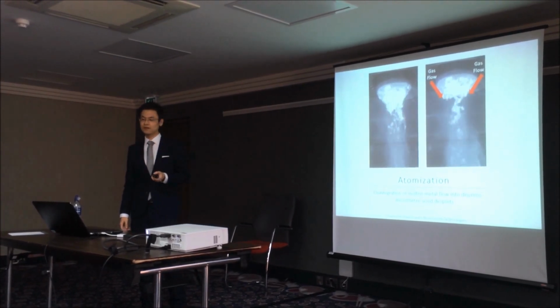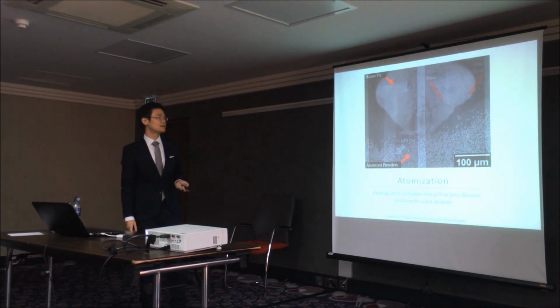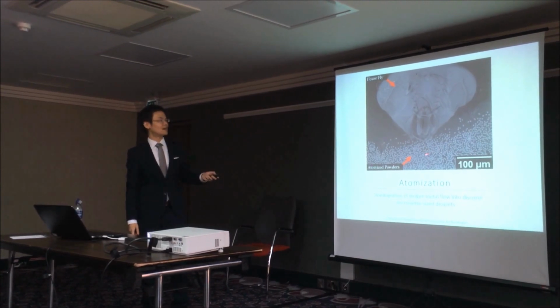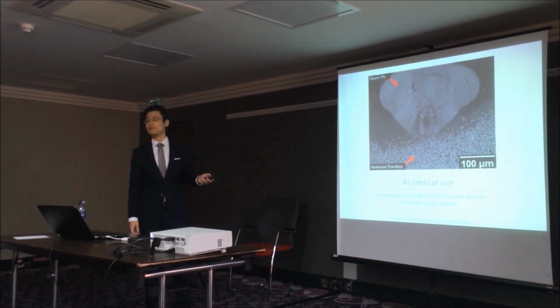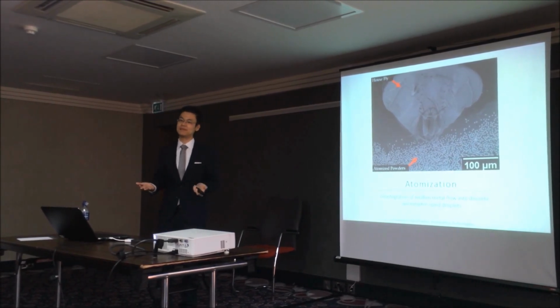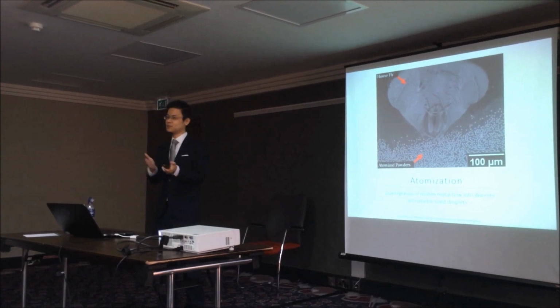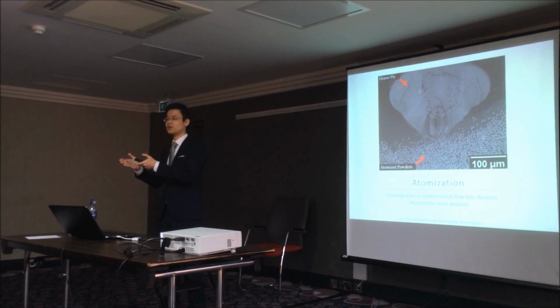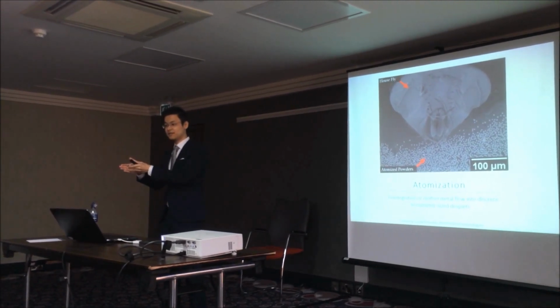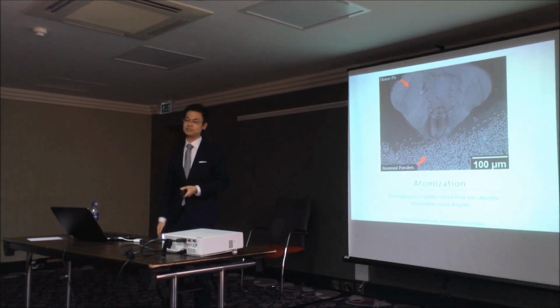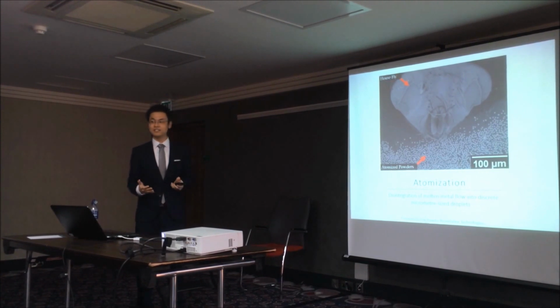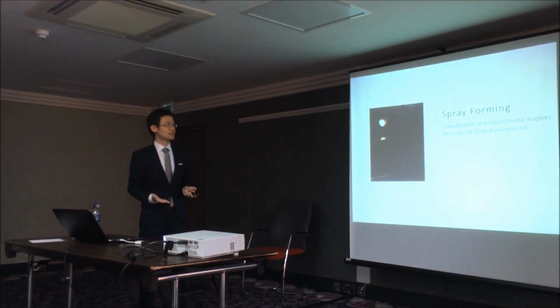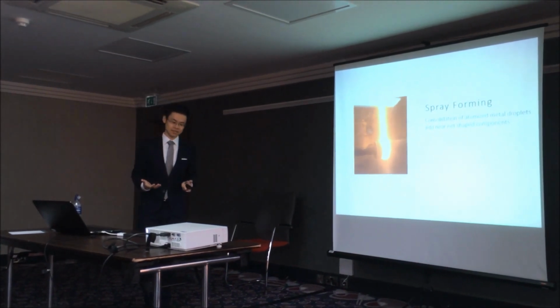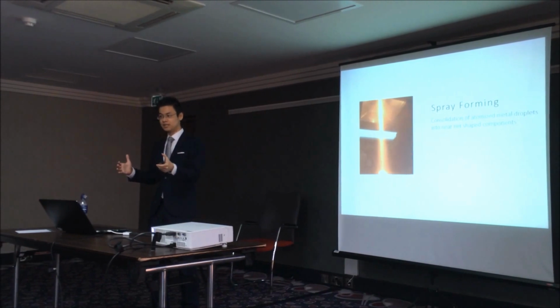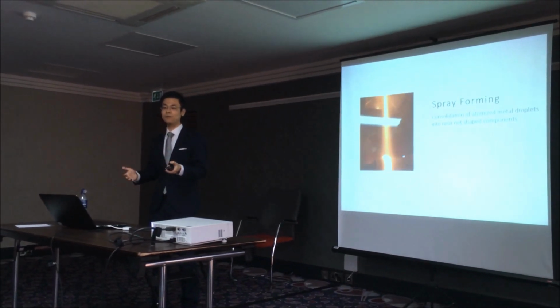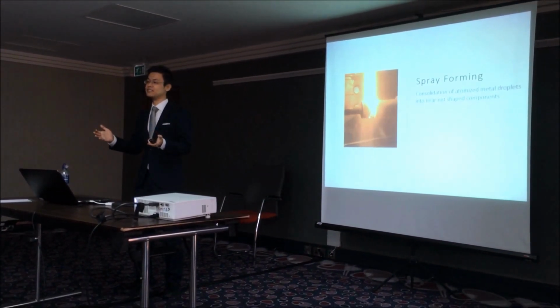Now, to give you an idea of the droplet sizes that we are talking about, this is the size of a typical head of a housefly. And these are the atomized powders or droplets, which is about 5 or 10 microns. For a typical spray, we can expect a droplet distribution size of 10 to 250 microns. And depending on this size as well, we could have a spray that has droplets that are solidified or in a semi-solid state with different liquid fractions. We can then harness the droplets in this spray by placing a substrate underneath the spray to form our component. Now, depending on how we manipulate the motion, the angle, and the shape of this substrate, we can then form components with different sizes and shapes.